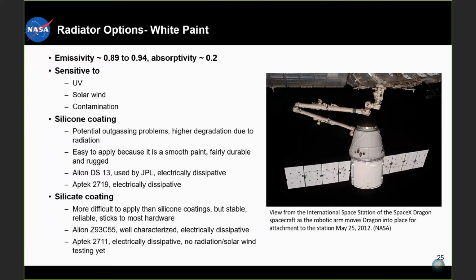So the next option for radiators is white paint. The emissivity value of white paint is about 0.89, again very high, to 0.94, while the absorptivity is very low at about 0.2. White paint is going to be sensitive to different things such as UV, solar wind, and contamination.